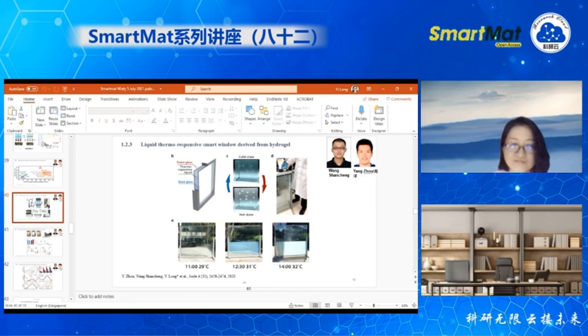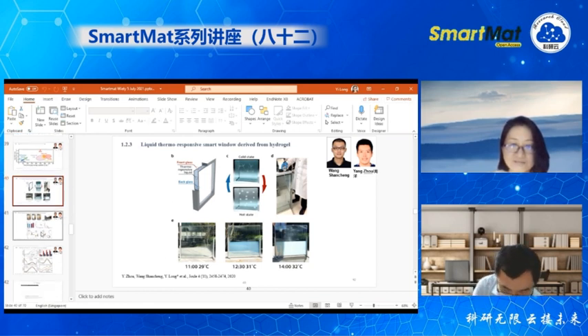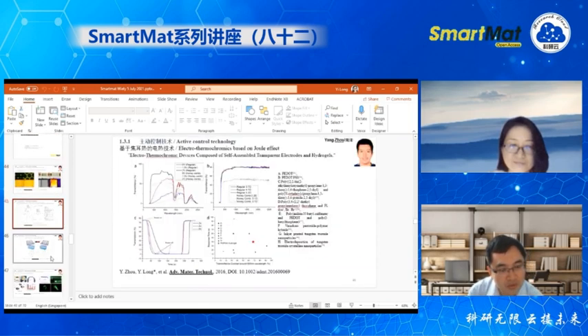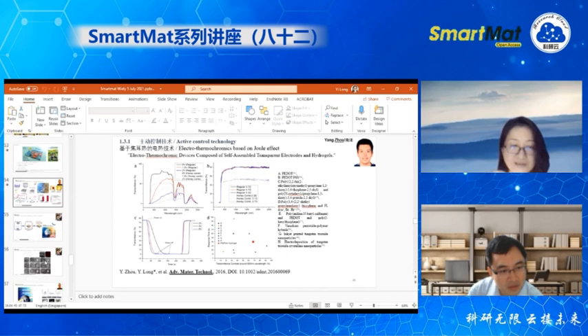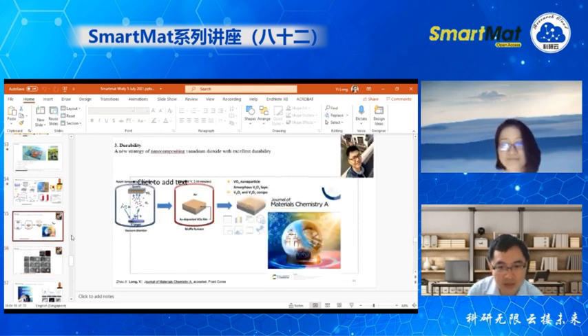Yeah, for the talk, the content about the durability. You use the VO2, right? And also the schematic for the structure. It seems your VO2 is wrapped by some other vanadium oxides. And V2O5, I know it's stable because vanadium has the highest valence in this material. But V3O7, I guess, is not the most stable phase of vanadium oxides. So is it possible to be oxidized during your durability test?